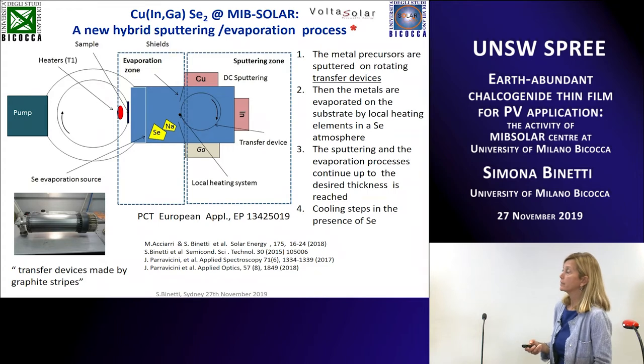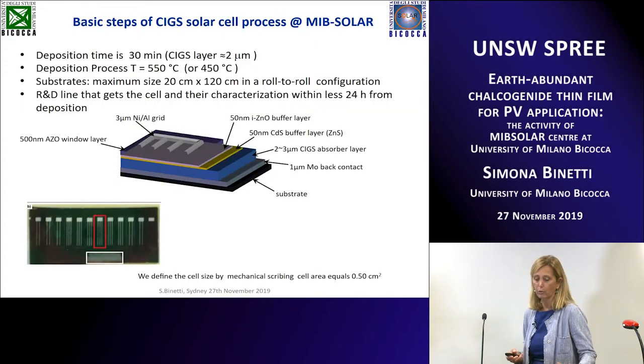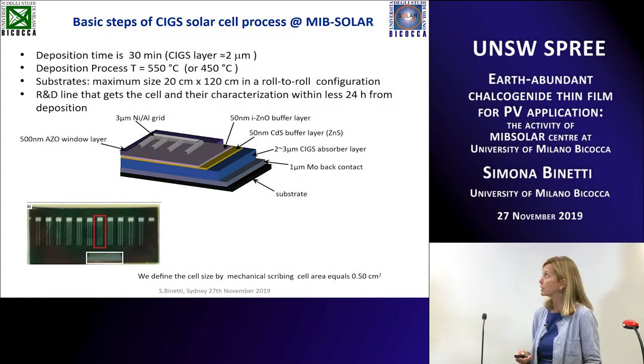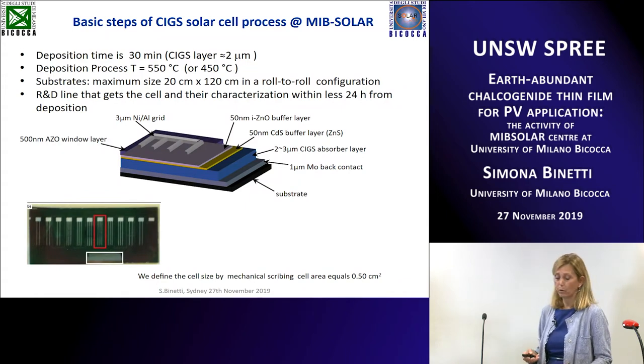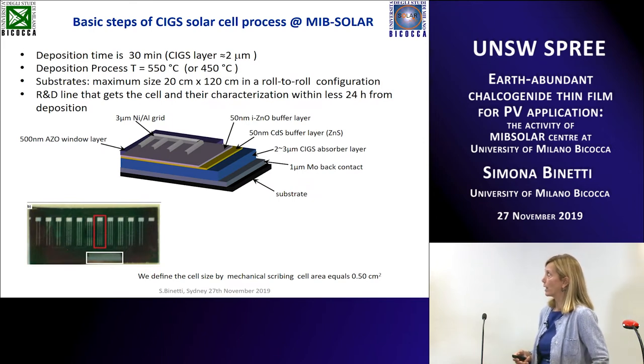Then we developed a system in order to have a sort of R&D line to check the quality of our machine, the quality of our material and our devices, meaning the efficiencies. So we have a deposition time in the order of half an hour, and the deposition process can be tuned between 550 degrees C and 450 degrees C when we have polyimide as a substrate. Then we can have different types of substrate in roll-to-roll configuration, or also standard 20 by 120 centimeters.